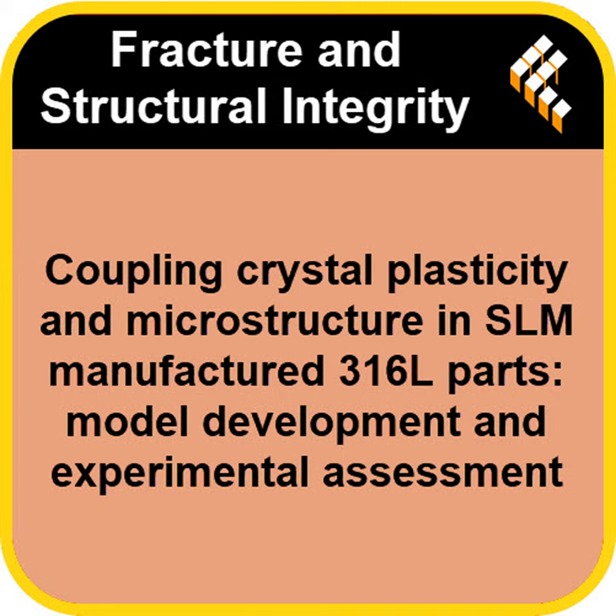And that vertical growth means the material is inherently anisotropic, right? Stronger in one direction than another. Precisely. And the measurements show it. The characteristic length of these grains is about 60 microns in the build direction, the vertical one. But it's double that, 120 microns, in the transverse direction. And it gets even more complex. Inside these big columns, there's a secondary cellular structure, almost like internal walls. Okay, so we've got a nested structure. Large directional grains with smaller cellular structures inside them. That sounds like a nightmare for predicting how stress will move through the part. It definitely complicates things. And that brings us to how this material actually deforms, how it starts to bend permanently.